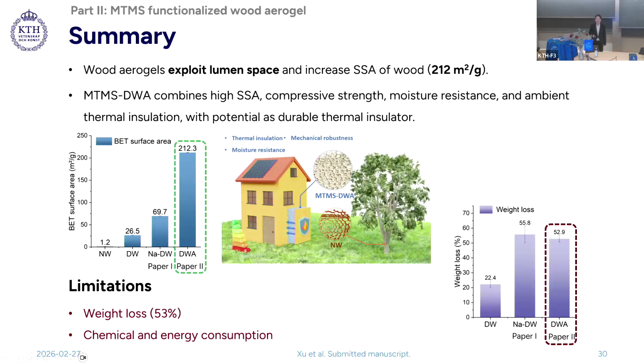However, the large weight loss is still a drawback. Besides, the chemical and energy consumption during chlorite delignification and the 24-hour cold sodium hydroxide treatment raise concerns. In paper 1 and paper 2, the cell wall nanoengineering relied on a two-step process, first delignification, followed by alkaline treatment.